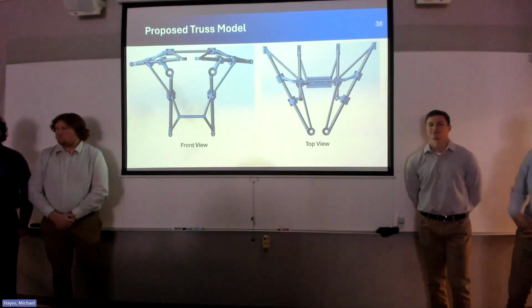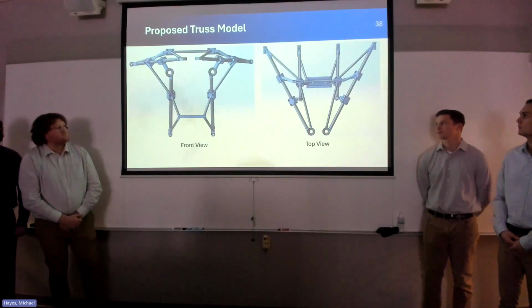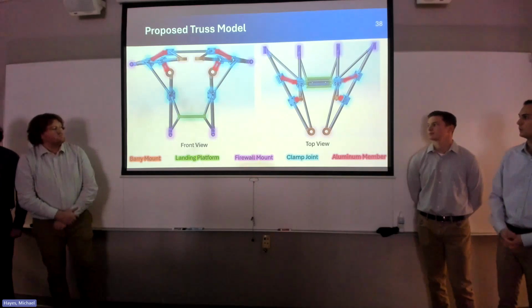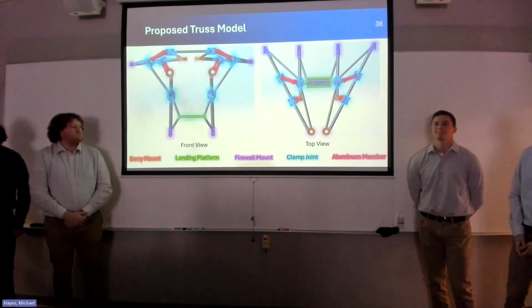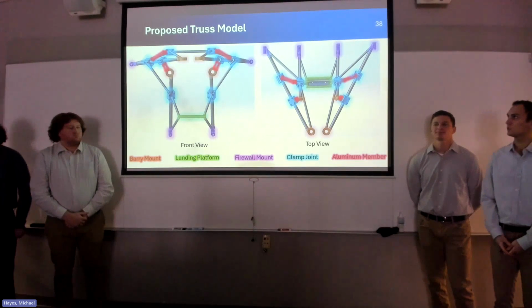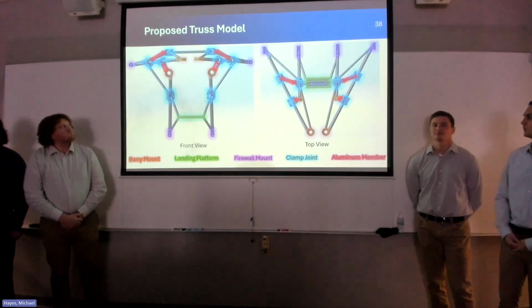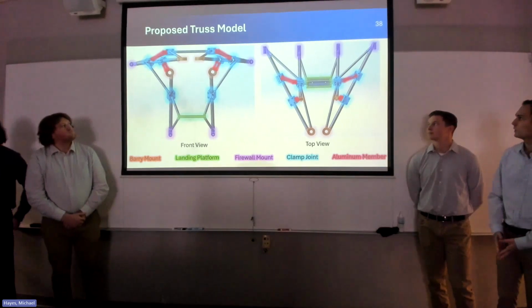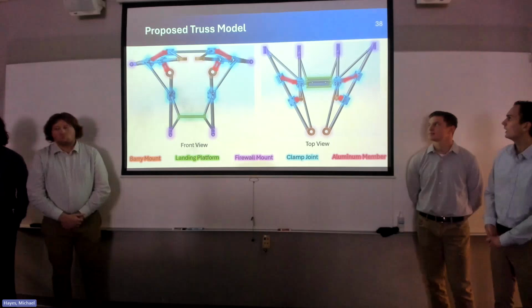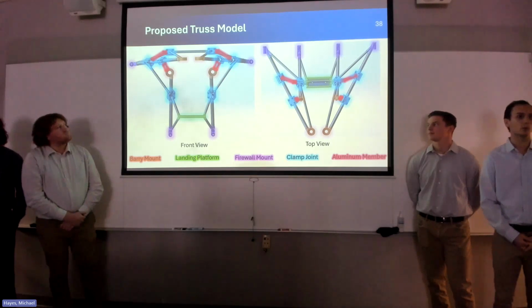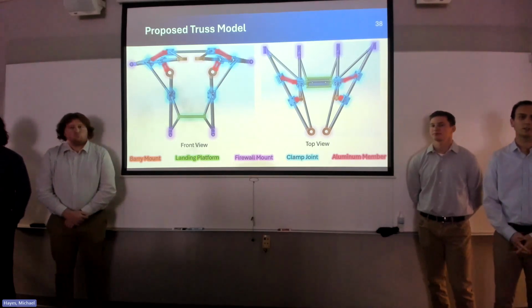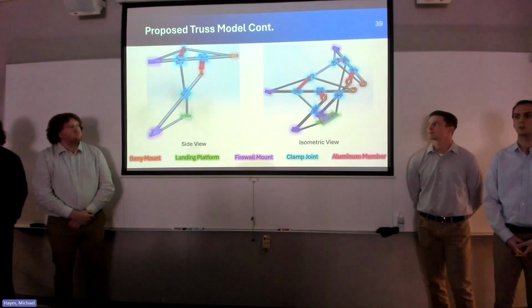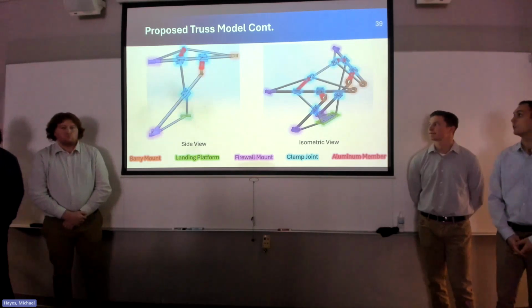Here's our final proposed truss model. As you can see, there's different highlights. The orange, green, and purple again are the mounting positions that are fixed, and we did not change those. And the blue are the clamp joints that Cole came up with. And the red highlights are aluminum members, which were members that were too short to fully utilize the effects of carbon fiber tubing. So they are aluminum tubing instead.